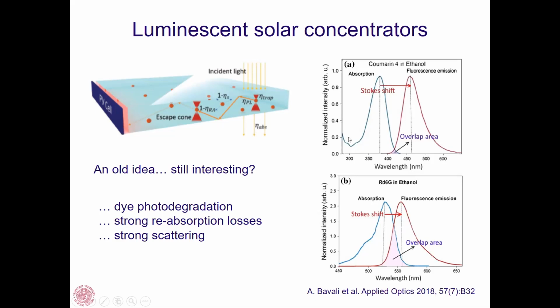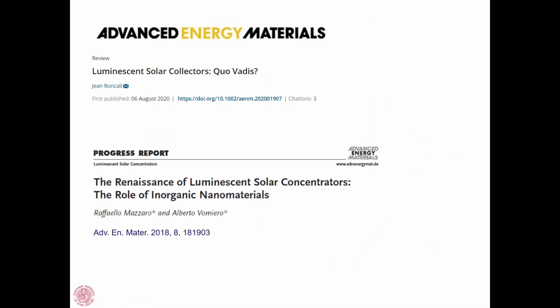So as you can see here, it's reported at two different levels of Stokes shift. And of course, when the Stokes shift is low, you have strong reabsorption of your light. This is reported for dye molecules, but the good point here is that by tuning nanocrystals, you can really tune the Stokes shift and obtain the results you need.